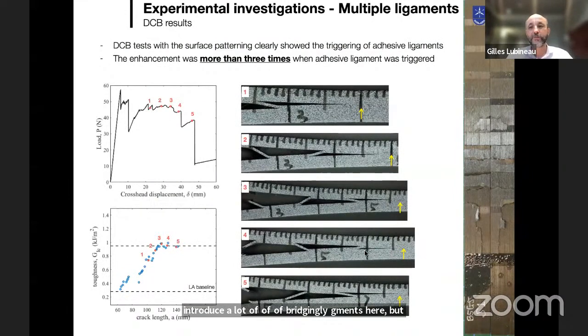If you look on the right of the screen here, what you see is a fractography of the interface. And you see here again that you have a lot of dissipation on the interface with a lot of bridging events and a lot of sub-cracks and so on. And you see this on the delamination curve. If I look at the delamination curve here, you see very clearly that the P-delta curve is much higher compared to the initial DCB curve, with a lot of secondary events.